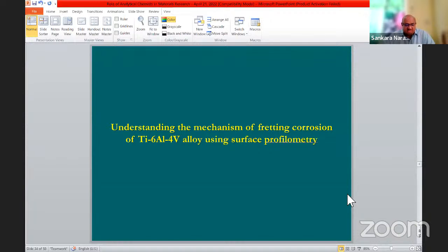Generally, implant materials are made of titanium alloy. And the fretting corrosion phenomenon, I already said, is a small amplitude vibration, small amplitude movement. Fretting corrosion in a titanium implant occurs mainly in hip, knee, and shoulder implants, where the human walking frequency is only about 1 Hz. With the small amplitude vibration, automatically fretting corrosion will come. If you look at the hip implant, it's a ball and socket assembly, just press fit. So there will be movement, and with time there will be fretting, mechanical damage, and there will be corrosion also.